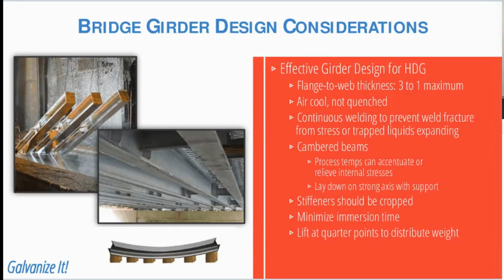If you're going to be looking at welding, especially overlapping areas, where possible use continuous welding or leave sufficient gaps, such as a 3/32-inch gap between overlapping surfaces. These can help prevent weld blowouts that occur when zinc cannot enter certain tight gaps between those parts. Next, be aware that galvanizing can potentially accentuate or remove a camber, but this may not be a problem as long as the diaphragm members can be attached in a way that can draw the girder into place.